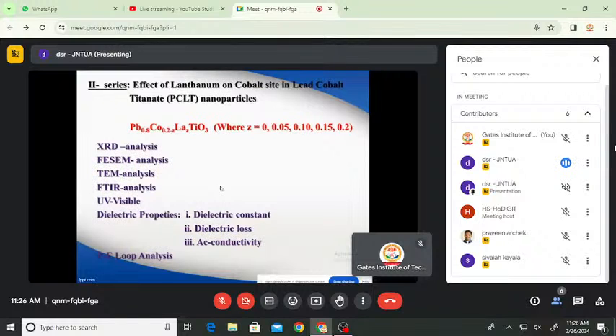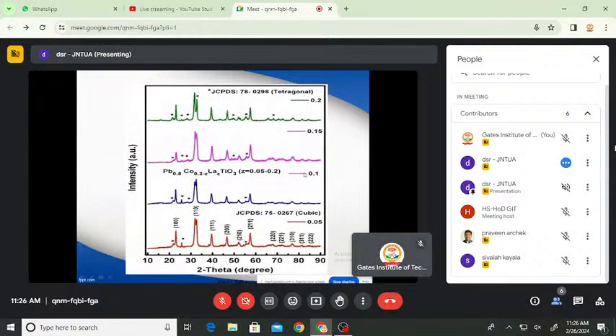So similarly, initially we synthesized PCT nanoparticles. Next, we synthesized lead cobalt lanthanum titanate nanoparticles. After varying the concentration from 0.05 to 0.2 and synthesizing, the samples were analyzed using XRD, FESEM, TEM, FTIR, and UV-visible, and we studied the dielectric properties and also the magnetic properties using hysteresis loop analysis. The samples were synthesized in a similar manner as the PCT nanoparticles, by the sol-gel method followed by micro heating.